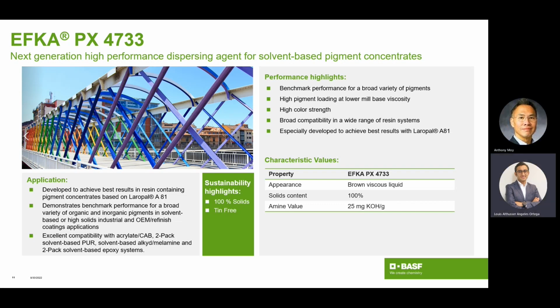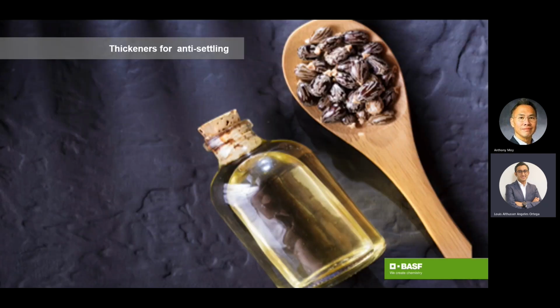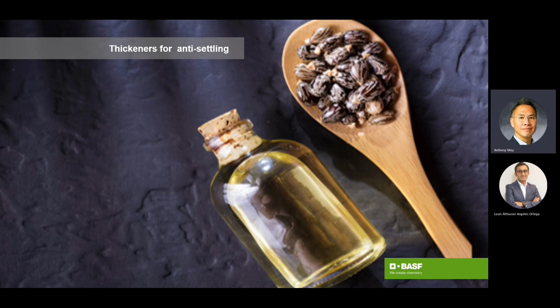So how can settling problems be addressed in an epoxy coating? Yeah, so one of the ways that we can address settling is by increasing the low shear viscosity of the formulation. By low shear viscosity, I'm referring to the state of a formulation as it sits in a container prior to use. So the only force being imposed on that formulation is really that of gravity. And usually during those situations, that's when your solid components like pigments and fillers have the likelihood of settling due to the force of gravity.